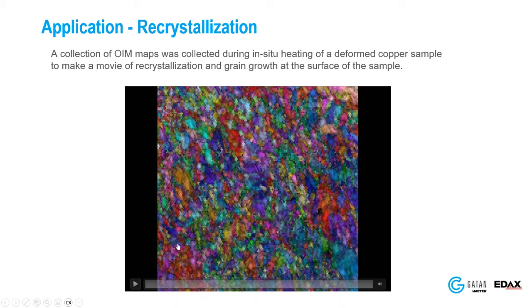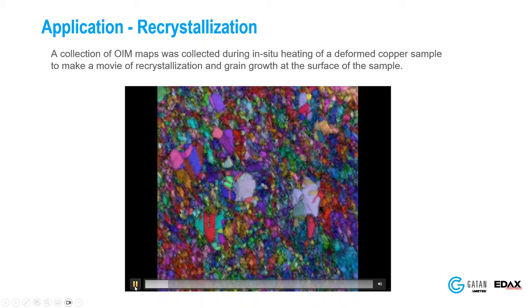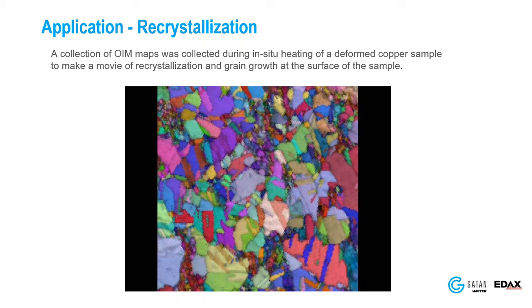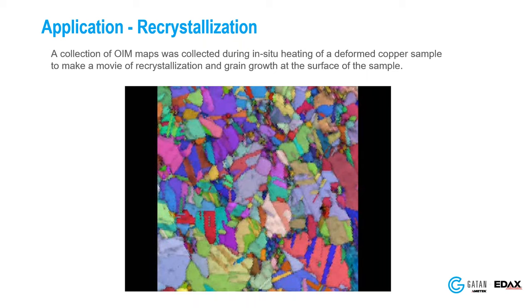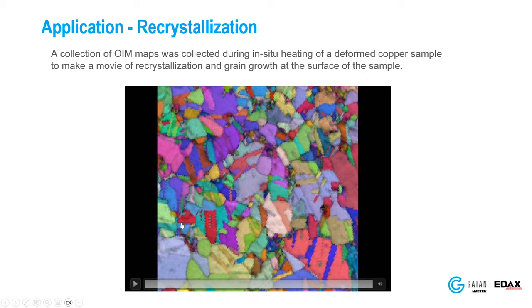Here's an example of dynamic recrystallization in an in-situ experiment where we heated up the sample. You can watch the grains start to grow. Some deformed areas take longer before they recrystallize, but eventually it will all recrystallize. It's a nice example of EBSD showing how deformation appears in these materials.